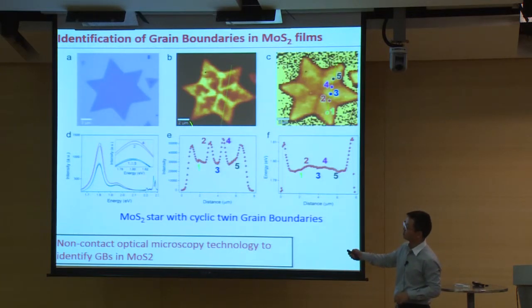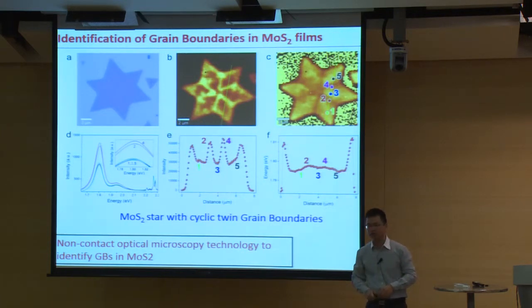Okay, this is a monolayer molybdenum sulfide star, and from the PL intensity mapping and the PL peak location mapping, we're able to tell how many grain boundaries we have, 6 here, and where they are. So this gives us a very quick and no-contact way to identify grain boundaries, and maybe very good for the device guys. They can know where they can put contacts on them.